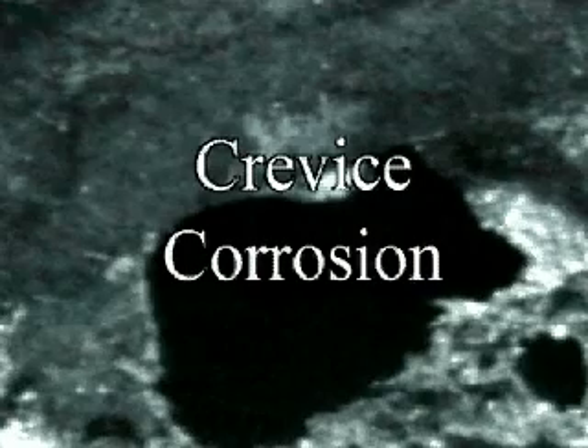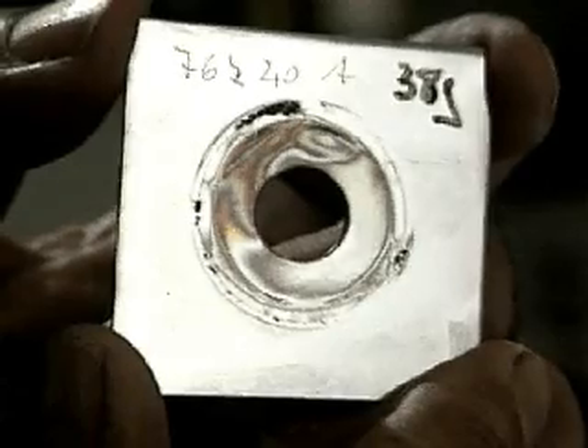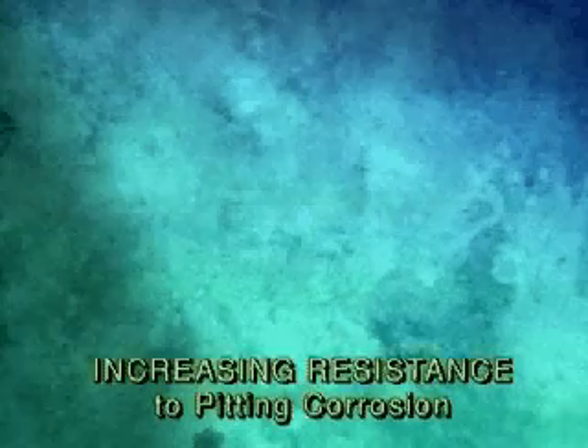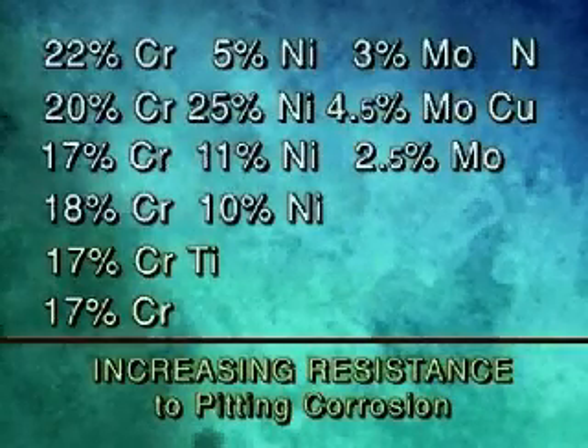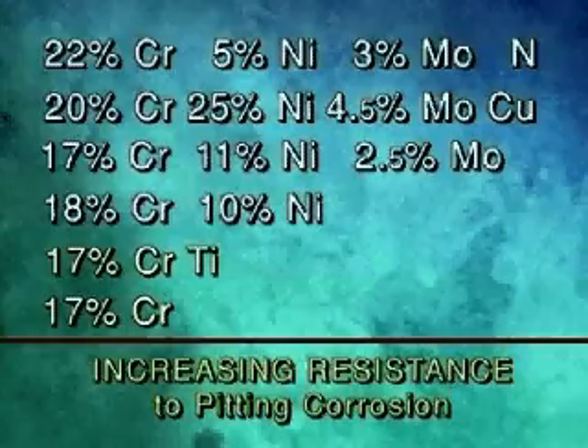Passive film breakdown may also occur in a crevice. In such locations, convection cannot take place, and only mass transport by diffusion is possible. When this happens, the local environment changes. The stagnant liquid becomes more acidic, and its metal chloride concentration increases. Eventually, the passive film becomes thermodynamically unstable and is destroyed. The unprotected surface then starts to corrode. This problem can be avoided by using a stainless steel containing higher amounts of chromium and other alloy elements such as molybdenum and nitrogen.